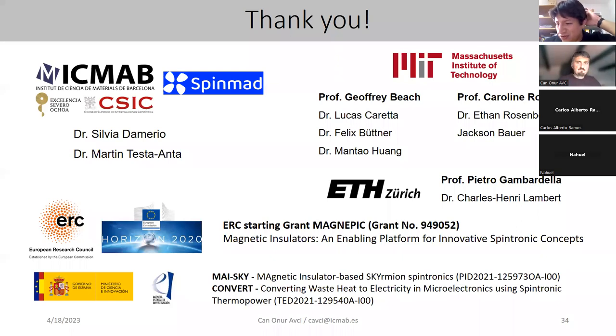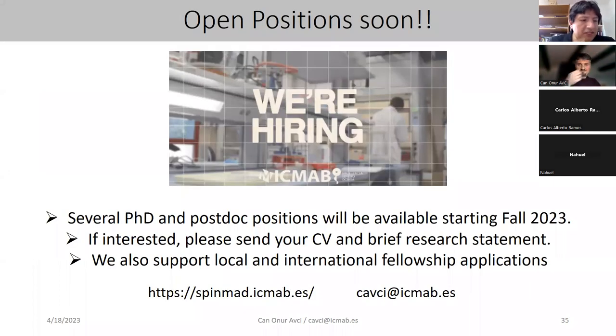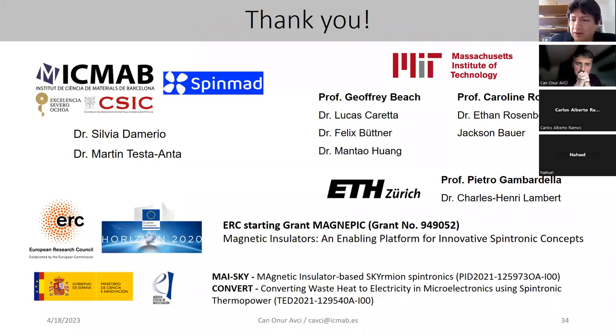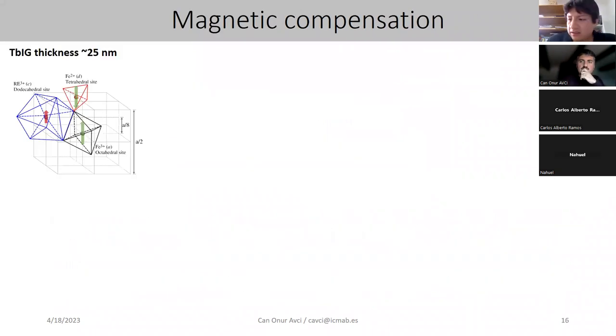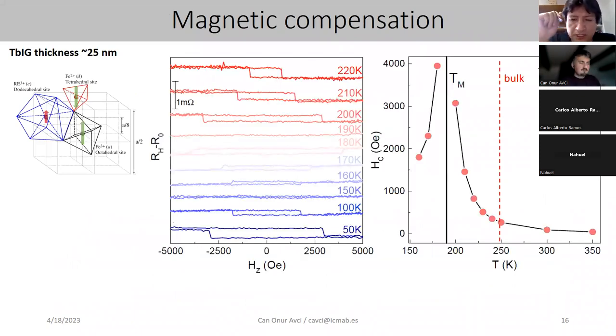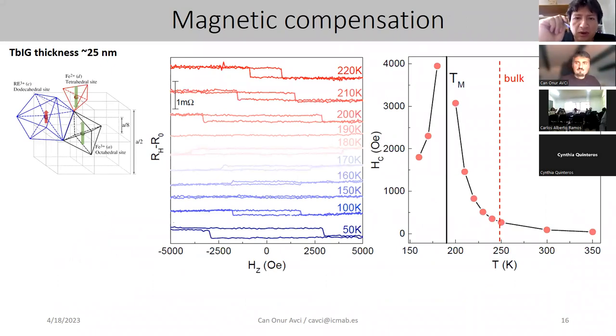Okay, I will start. First, in slide 16, you show you try to determine the compensation temperature of your garnets. You can go back to that slide. In that one, you mentioned that at 250 is the compensation of your bulk. Then at 190 degrees, you have the divergence of your coercive field. But at 150K, you also have a reduction of the magnetization. What does this mean?